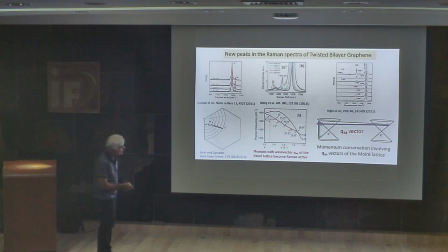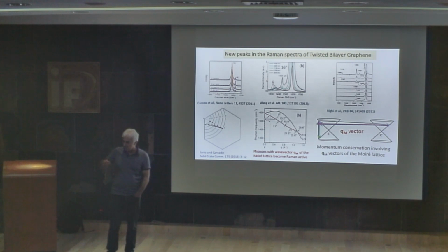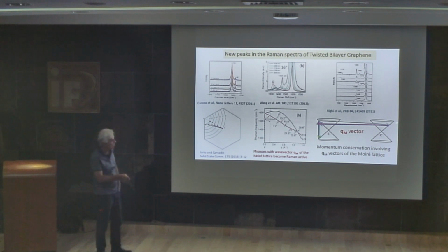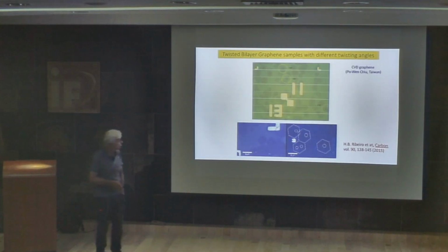Okay, then in this paper in 2011 from our group, we proposed that this process was similar to the process of the 2D and the D band, but instead of having a defect or a second phonon to scatter back the electron from this point to that point, the electron was scattered elastically by the moiré pattern. Then the moiré pattern provided elastic scattering to bring back the electron from one cone to the other cone.